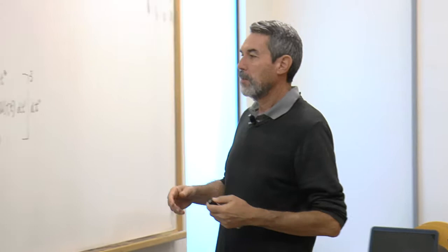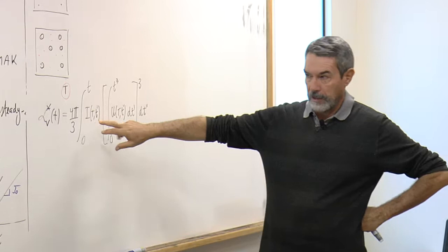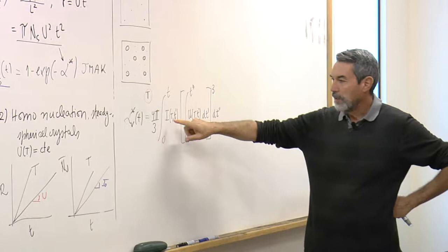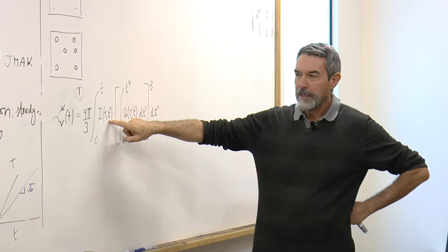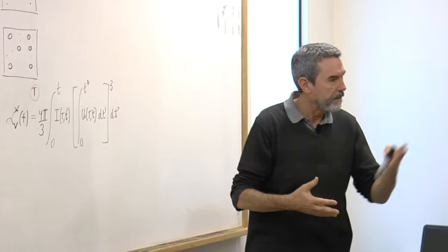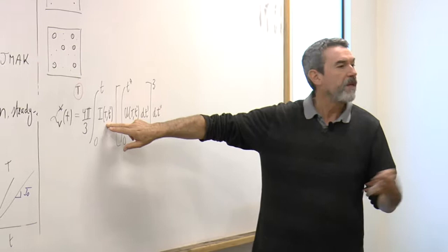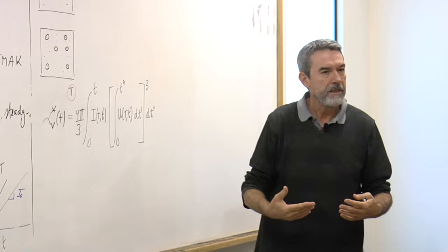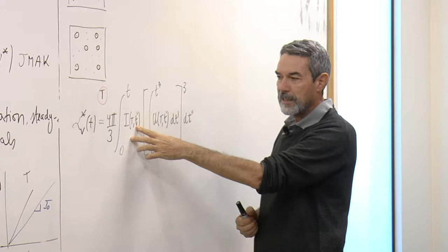The problem here is simplified by the fact that I have said in the boundary conditions that we are working with steady state conditions. So the nucleation rate and growth rate do not depend on time for this particular boundary condition. This is the general equation for any condition. When we have non-steady state effects and things like that, we have to take the full expression of Kashchiev here, for instance. But in this case, I have simplified. I said that I does not depend on the time, only the temperature.